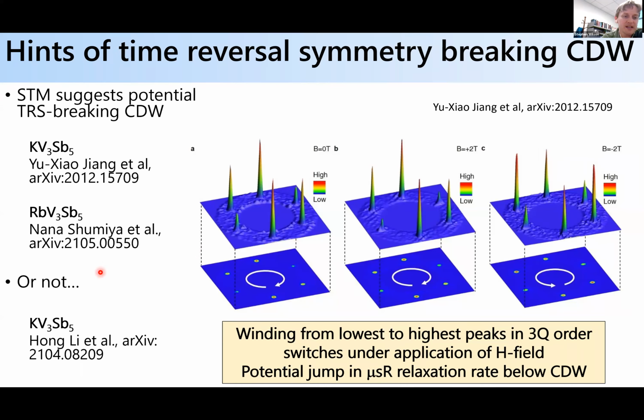So I want to add here that it's not universally agreed. For instance, there's another work on potassium vanadium-3 antimony 5 that doesn't see this type of magnetic effect. And I think that's something that's going to get worked out in the coming months, probably. I think the claim is that it's not a sample effect because we provided samples to both groups. So it's the same samples. It's just however the STM is preparing the surface might make a difference, or I think in some cases, some people are concerned about tip effects in this particular measurement.